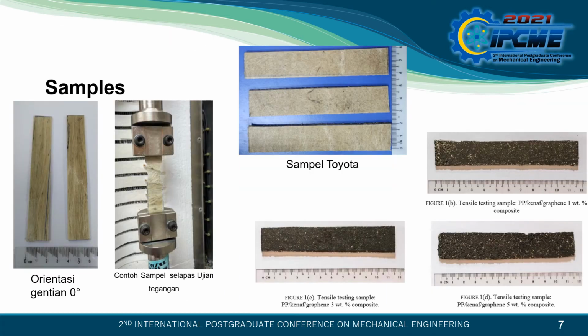Here on the right are the samples using this short Kenaf. As you can see, we add graphene as a secondary filler, you might add CNT or carbon black. The purpose, other than increasing the mechanical performance, was to improve the aesthetic value. We want to see the color turn black, compared to the basic base of polymer and Kenaf itself, which is a very plain brown color.